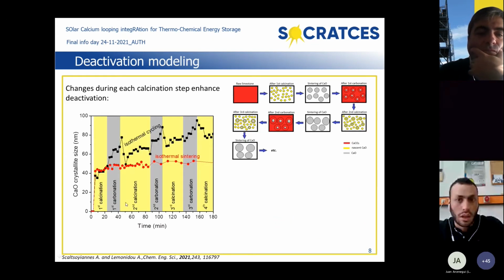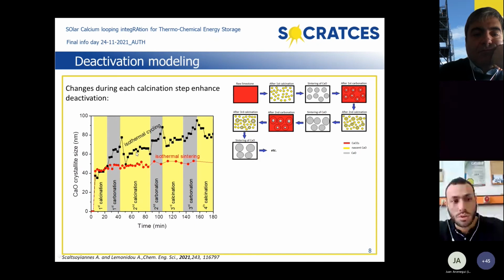And more specifically, we carried out in situ X-ray diffraction experiments, where in the first case, the material was first calcined and stayed in calcium oxide form under sintering conditions, while in the second case, the material after the first calcination was subjected to successive calcination and carbonation steps. So here is the evolution of calcium oxide crystallite size in these 2 treatments, and you can see that when the material is cycled, the calcium oxide crystallite size increases after each calcination step.